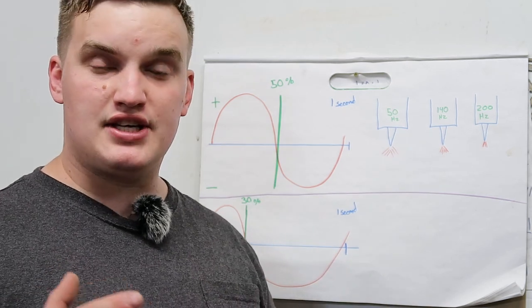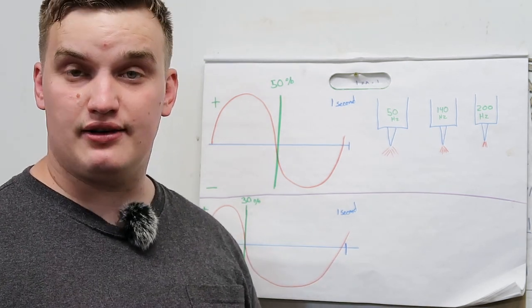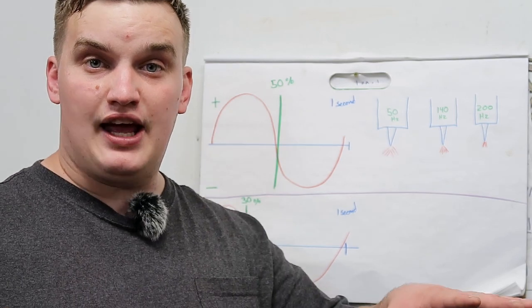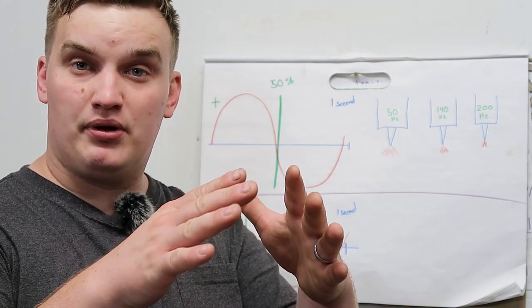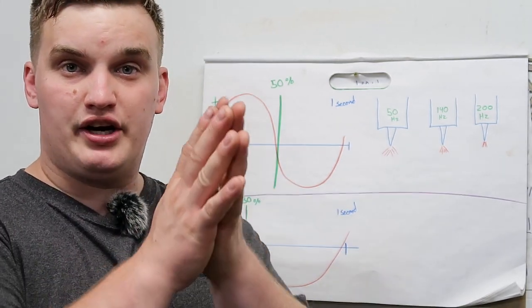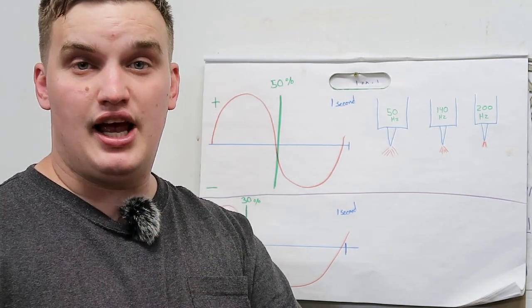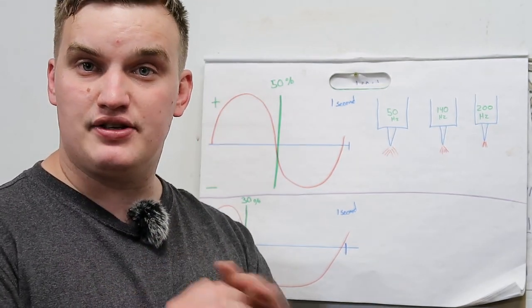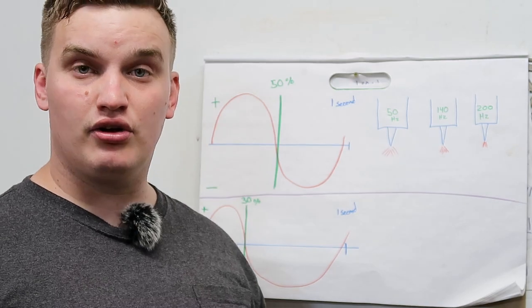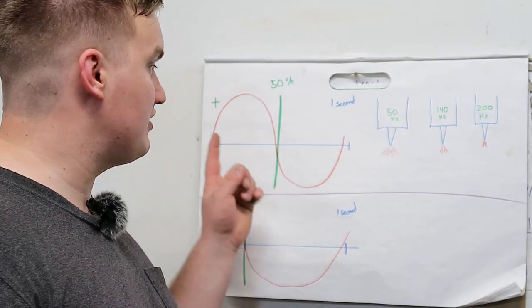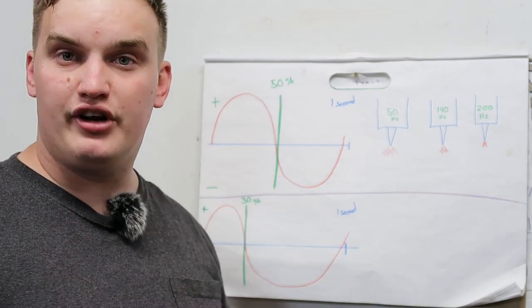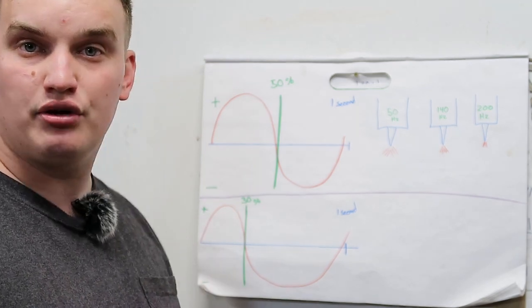And vice versa, if you just had it set on DC positive, that amperage would be coming off the surface of your workpiece, and that current would be trying to get up into your tungsten and balling up your tungsten, and you would be getting zero penetration into your material and just making a mess. So this is why it's important to have our alternating current. They both serve a good purpose.